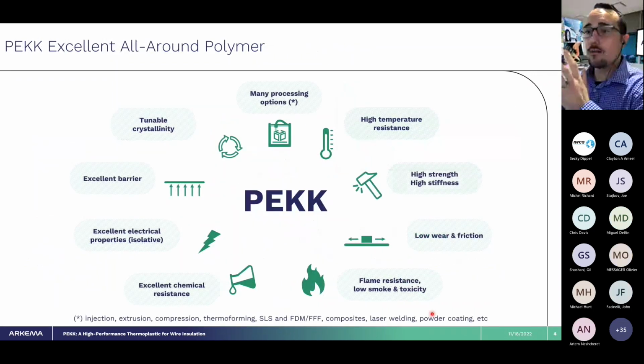So all around, this is an excellent polymer for a number of reasons, and I'll kind of walk around this circle a little bit. High temperature performance, so continuous use temperatures in the order of 260 degrees C, upwards of 300 degrees C for transient use. It's high stiffness, 3.9 or so GPa in stiffness, high strength, great wear properties for things like powder coating or wire coating when you're worried about abrasion resistance.